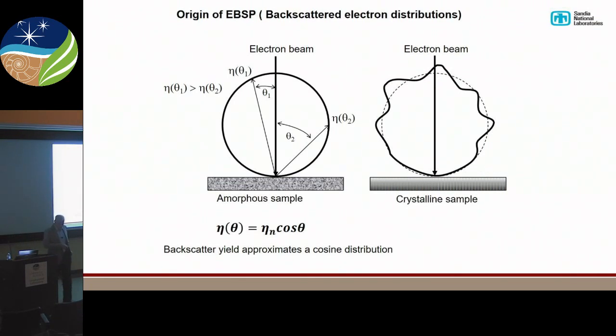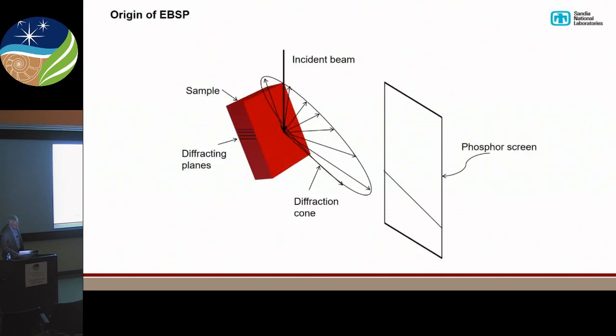So how does this actually work? We take our electron beam. In a normal SEM, if we illuminate an amorphous sample with electron beam, we get this distribution of backscattered electrons. If we then do that with a crystalline sample, you can actually see that there's perturbations on here. And this is schematic, but people have actually done this experiment. Those perturbations are due to Bragg diffraction in those directions. Okay, so we're seeing now the influence of Bragg diffraction on our backscattered electrons. And that's really the basis for this technique.